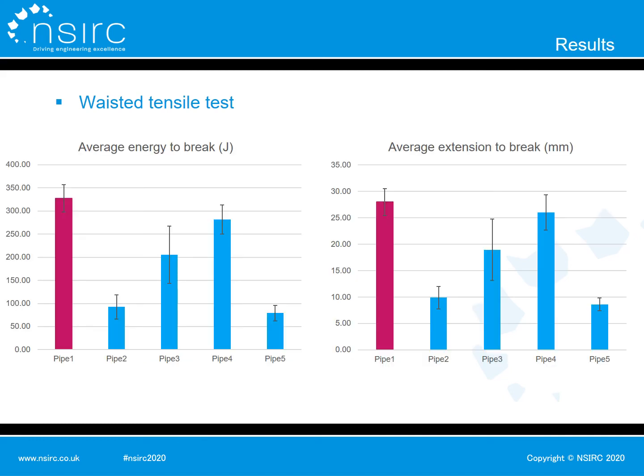Now let's have a look at the result of the waisted tensile test. As expected, the average energy to break and the average extension to break of pipe 1 with no windows is the highest. Pipe 4 with low level of windows has the best performance of all pipes containing windows, but the properties of pipe 4 are still a bit lower than those of pipe 1. Pipe 3 with medium level of windows gives a medium performance with large deviation. Pipe 2 and Pipe 5 with high level of windows have the lowest energy to break and extension to break.